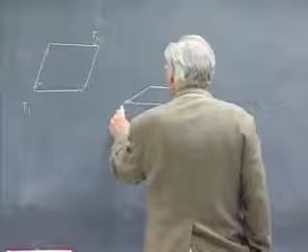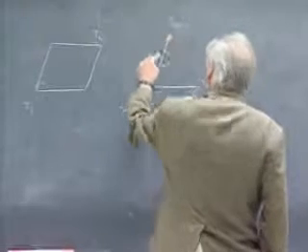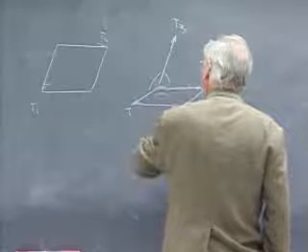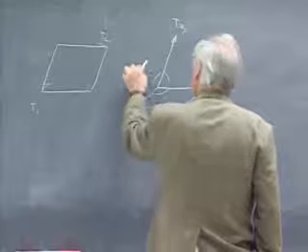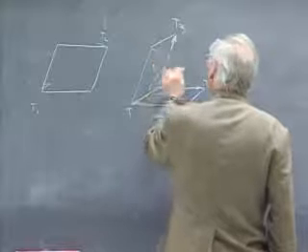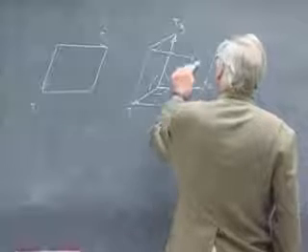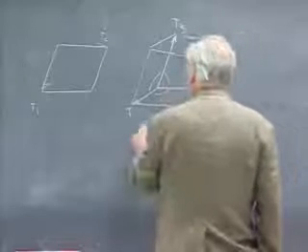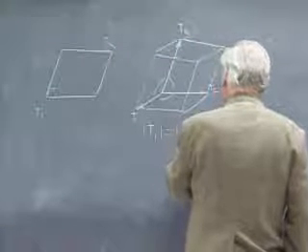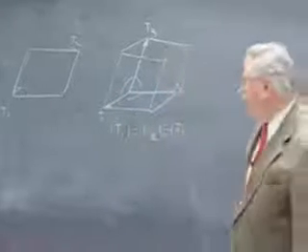If this is T1 and this is T2, T3 can be in any orientation such that not only is this angle general, but this angle is general and this angle general as well. And if I would try to carefully complete the parallelepiped so that its geometry looks reasonable, this is going to be a general oblique parallelepiped with 3 translations that are unequal in magnitude and 3 angles between these translations.